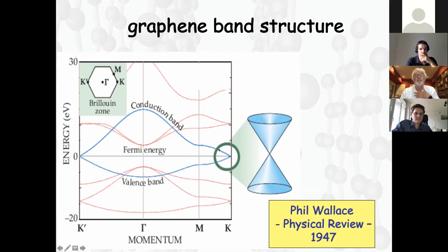So this additional degree of freedom that forms the conduction and valence bands of graphene can be understood as the sublattice degree of freedom of a single graphene layer. So there are 2 states in this low energy range of interest in a single layer. And if we have a bilayer, then we have 4 bands. And that means that our model of twisted bilayer graphene has to be a model with a periodic Hamiltonian involving 4-component spinors.